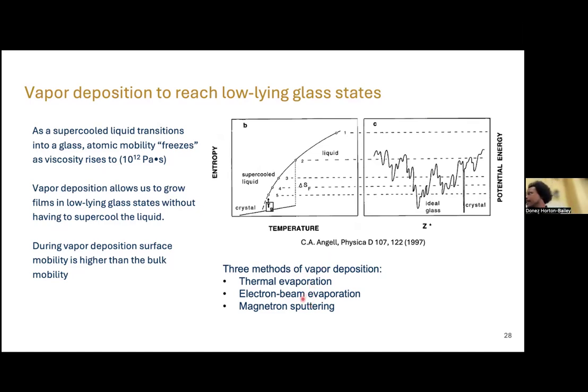Our lab focuses on 3 different methods. Thermal evaporation is the simplest. You heat up the material until it melts or until it vaporizes or sublimates. It creates a plume of atoms, and you put your substrate at the top, and all the atoms attach to the substrate. Electron beam evaporation, instead of heating it up, you have a beam of electrons that you accelerate with a magnetic field. You hit your source, it knocks atoms off of your crystal source, and then hitting the substrate, you form an amorphous film. And then third is magnetron sputtering.